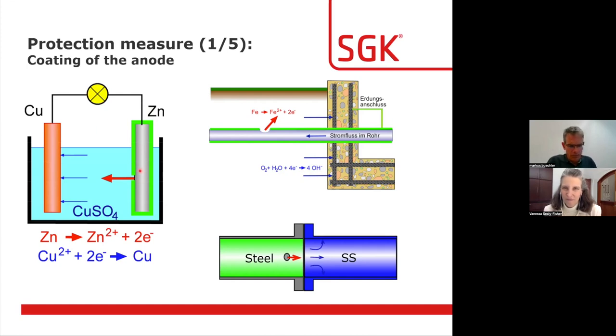And one of the solutions that is often taken is to coat the anode, which at first looks like an excellent idea, because the idea is to separate the metal from the electrolyte. But unfortunately, it's technically impossible to make a defect-free coating. So you actually end up with tiny holes in the coating with very high current density, still considerable current flow, and actually even faster perforation of the zinc than what we would have had in the uncoated state. So imagine you have a pipeline uncoated, you have a huge anode, corrosion rate is relevant, but pitting takes tens of years.